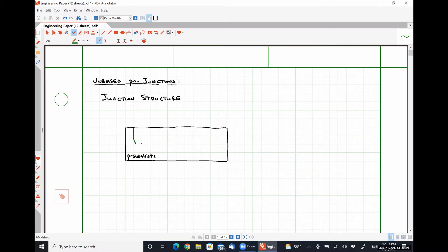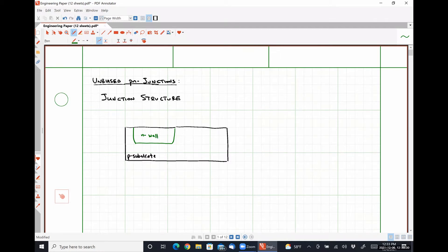I might have something like this — it's not going to be a purely rectangular profile because of the annealing process. It's going to have slightly rounded edges. This region of the crystal would be what's called an n-well. If my substrate was doped at 10 to the 15 acceptor atoms per cubic centimeter, my n-well needs to reach 10 to the 15 donor atoms per cubic centimeter just to behave like an intrinsic crystal, and then go even past that to behave like n-type.